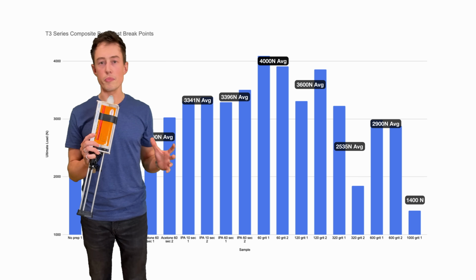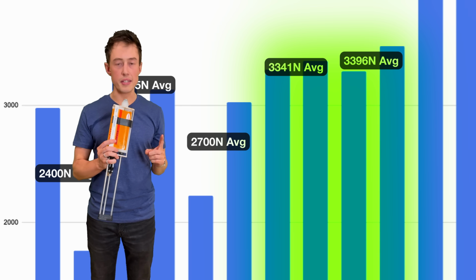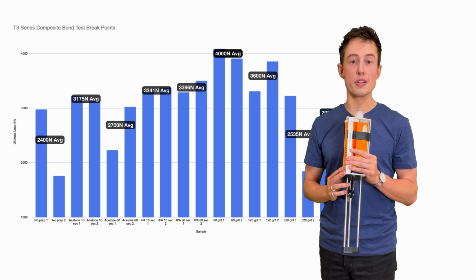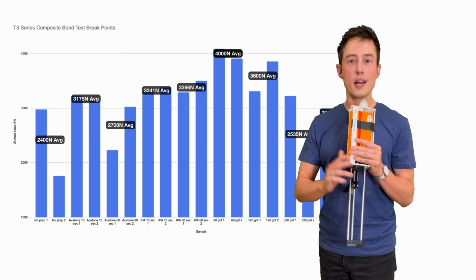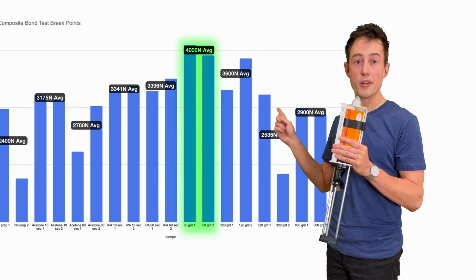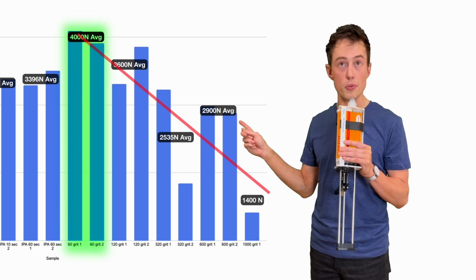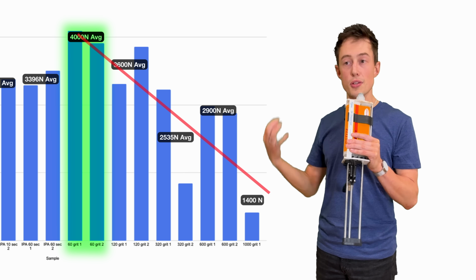So what can we learn from this? First, I like how consistent the IPA was. Consistency is important, and we will come back to that later. Second, I'm impressed by the 60 grit strength, and there does seem to be an inverse correlation between the grit size and the total strength of the bond.